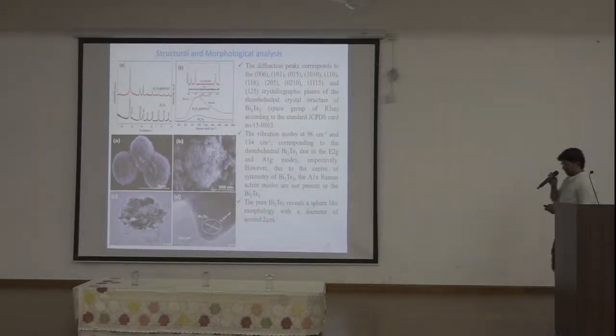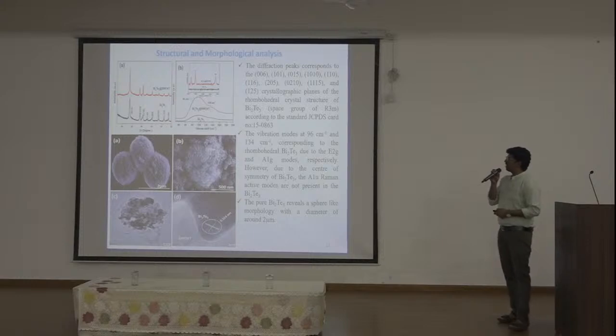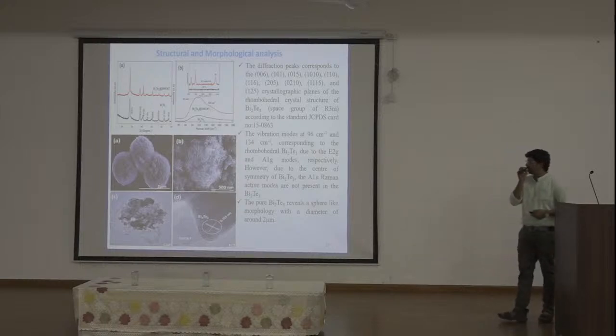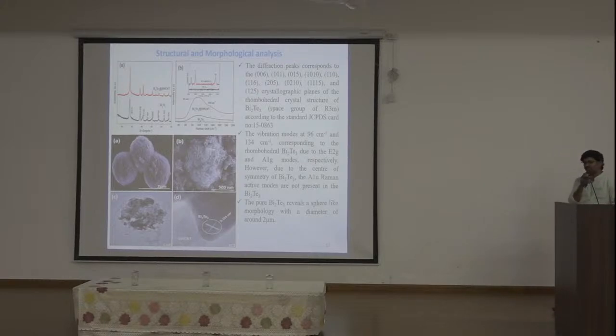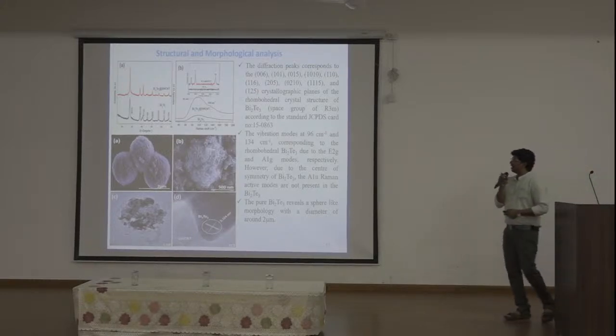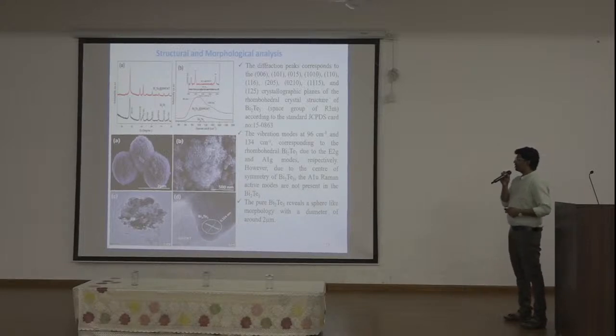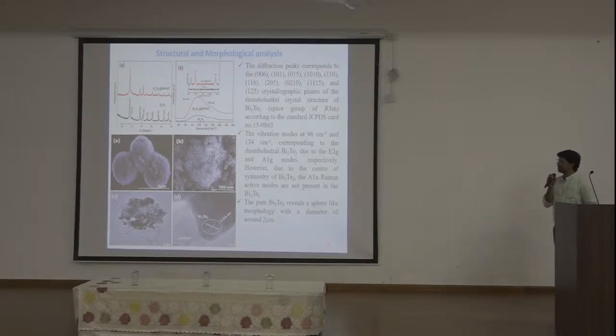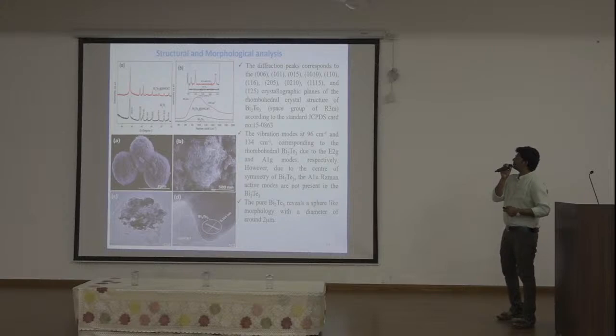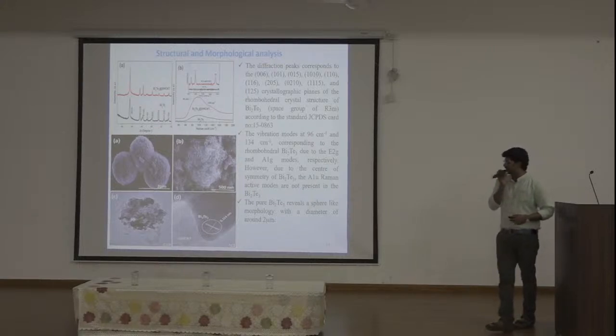This is the basic XRD spectrum and fundamental analysis. After inclusion of SWCNT, there is no change in the peak position, but peak broadening happens in the bismuth telluride SWCNT composite. It indicates that the CNT is attached in this composition. We can also see the Raman spectra along with the characteristic vibration modes of bismuth telluride. The D band, G band and 2D band are present, which also indicates the CNT inclusion in this composition.